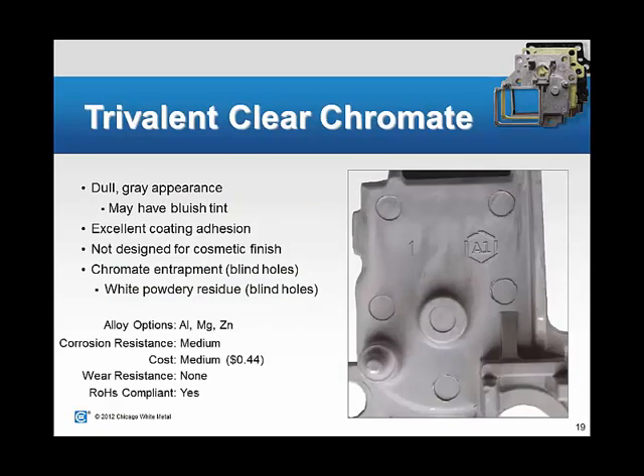The first option that we look at is a trivalent clear chromate. It has a dull gray appearance, and can have a bluish tint at times. It's very inconsistent from batch to batch exactly how the parts come out and look. It does provide excellent coating adhesion for the following finishes that might be applied to this part. The two things to consider when looking at pretty much all of these bath-plated processes are chromate entrapment, and a white powdery residue that can be an issue if the part has blind holes. You can imagine if a part is racked and then lowered into a bath, sometimes blind holes have a hard time receiving the liquid into them, and then a hard time getting that liquid back out. So it's just something to consider. Proper rinsing of the parts after the process will typically alleviate that, but just something to consider.